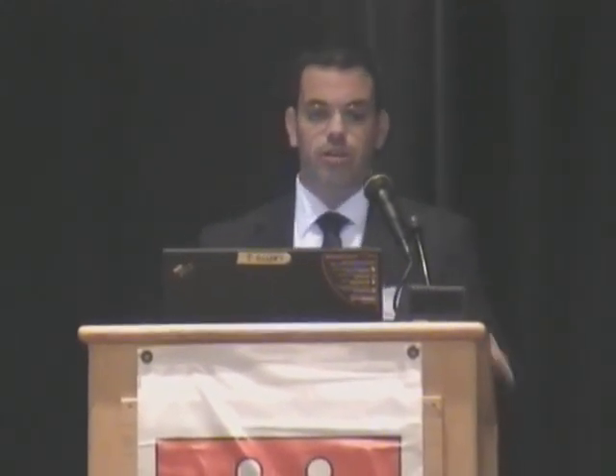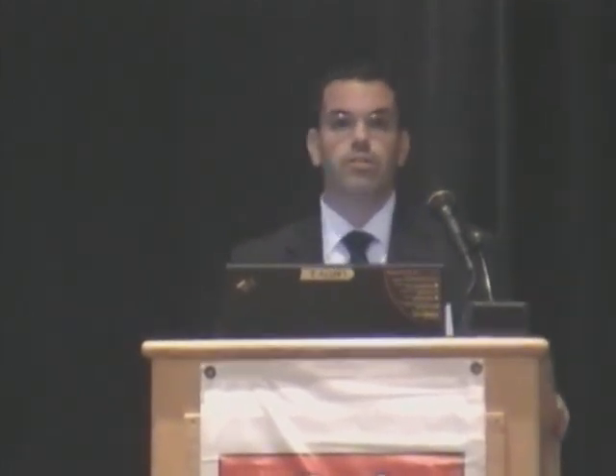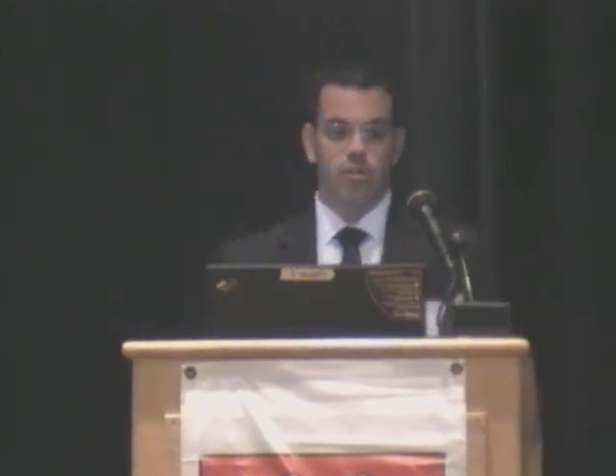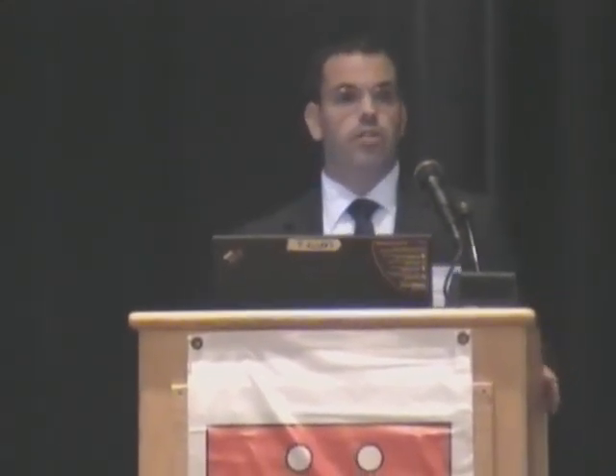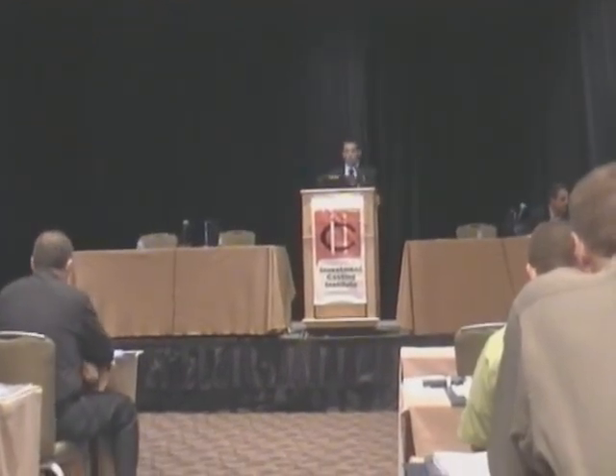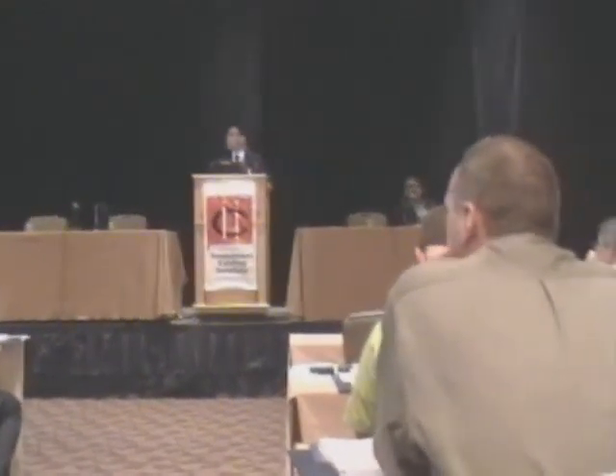Then on step 4, which I will discuss a little bit more further in those slides, was running the improvements. So we went into our process departments, which are, I can say, the 3 process departments in the foundry. First of all, the heartbeat, was the foundry itself, trying to gain better control on our melts. And then the wax assembly room, in which we were trying to look at our methods and practice in gates and runners, how we assemble actually. And then finally, and maybe the most intimidating, is the shell department. Going into slurry compositions, the drying cycles, the layers, the amount of layers, the sands, the refractories, everything we've been using in the past more than 20 years, I guess. Then finally, getting control of another thing that we actually did, instituting a production continuous improvement team to monitor those changes we ran.